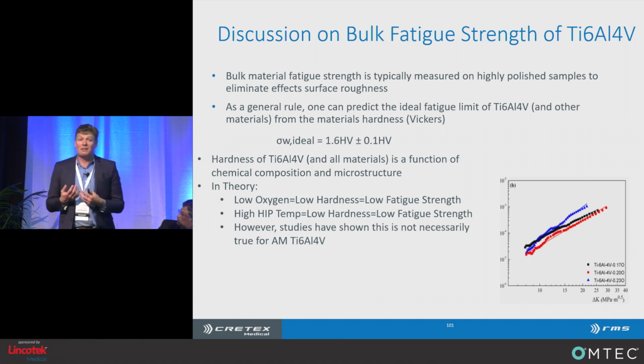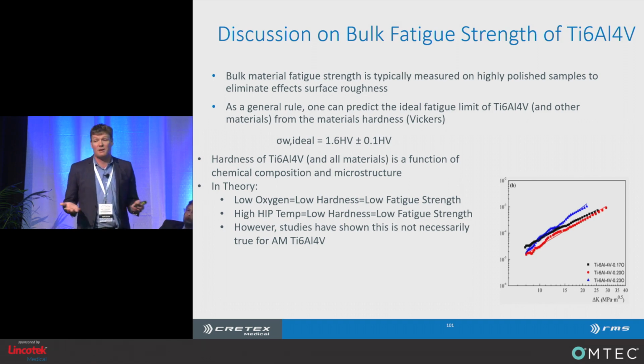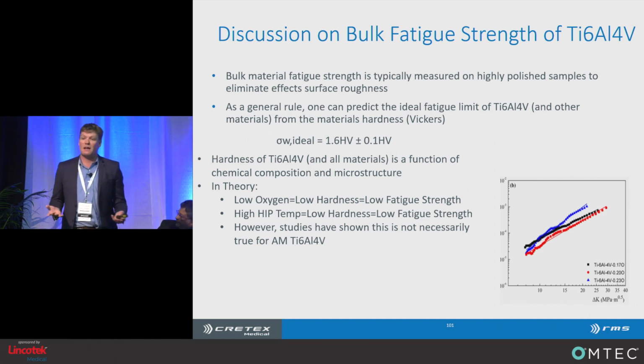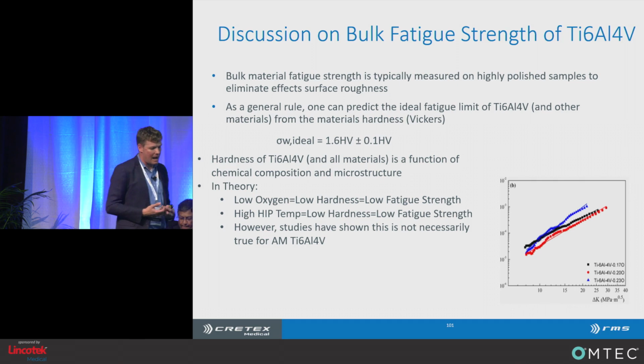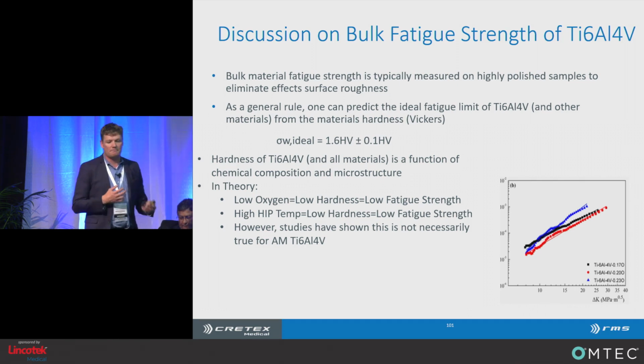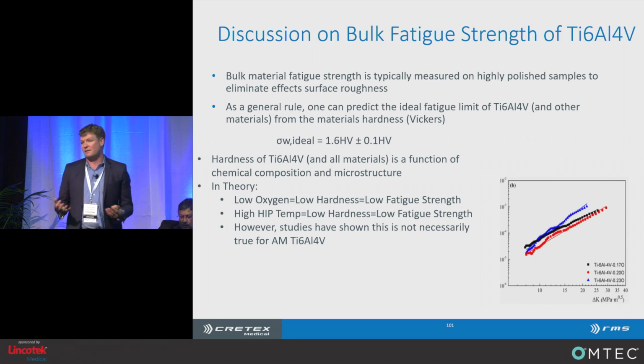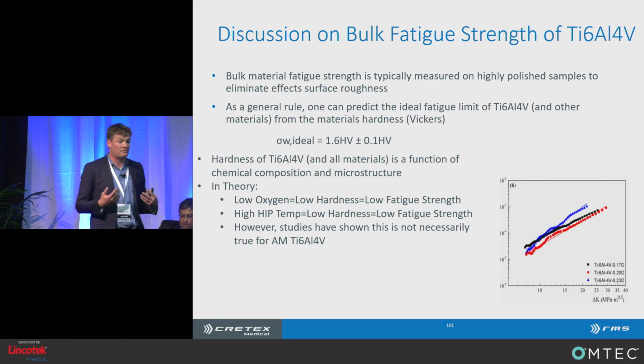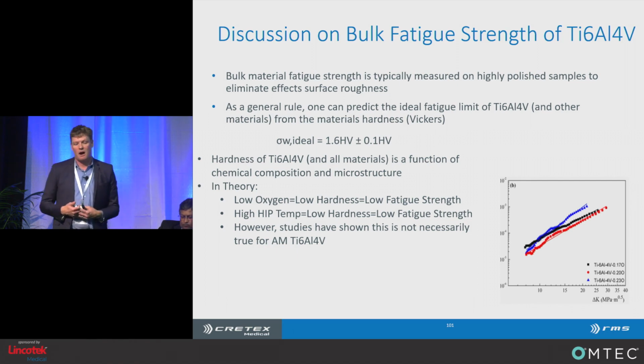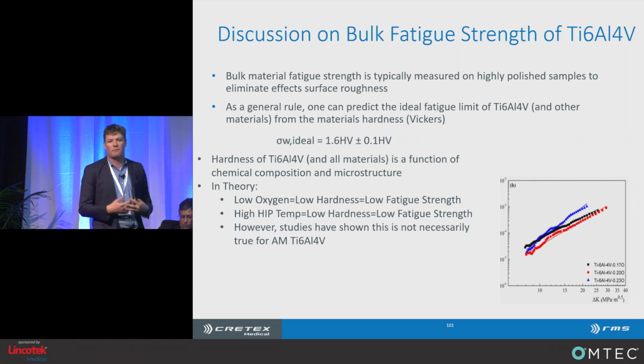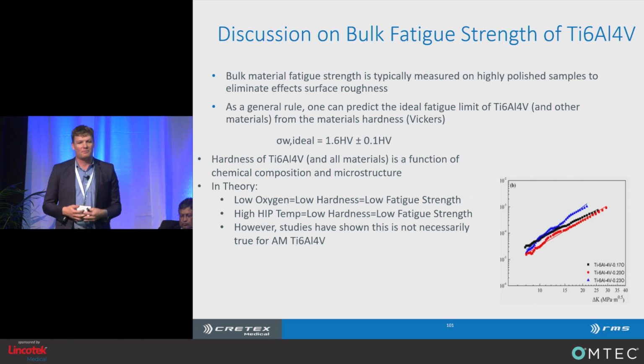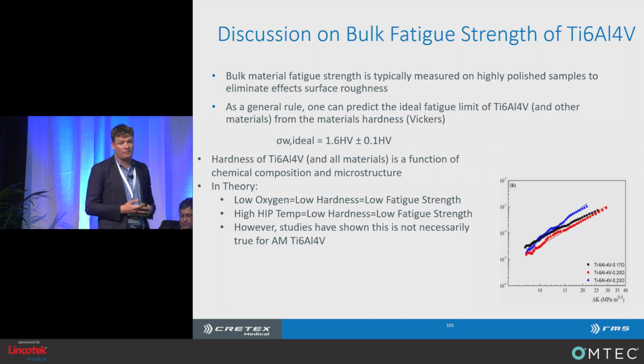And in general, you can predict the bulk fatigue strength of a material based on its strength and its hardness, perhaps, right? So we have all these perceptions about how things like oxygen content and heat treatments can affect the fatigue strength of Ti6Al4V based on all the information we know from years of history with wrought. But those don't necessarily correlate to additive manufactured Ti6Al4V.